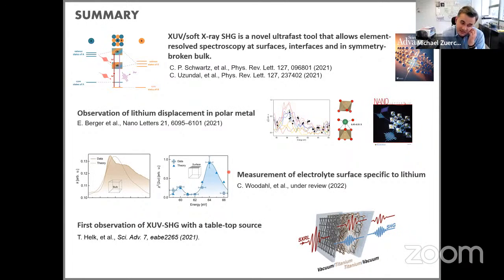And actually, yes, we see that in the experiment. I think it's in the SI. To make sure that this is actually coming from the phase transition, what we did in the experiments is to measure first at room temperature, and then while we cooled down the sample, we looked at the second harmonic. Once you go through the phase transition, you actually see the second harmonic popping up. So this was also an affirmation for us that this is really the bulk state, which comes from the symmetry breaking. And we did not see any second harmonic when it was in the symmetric state.